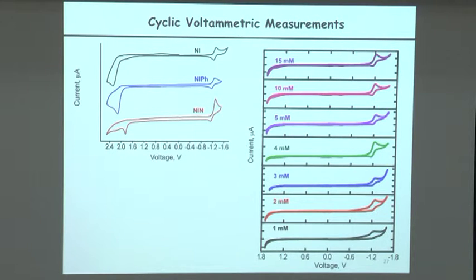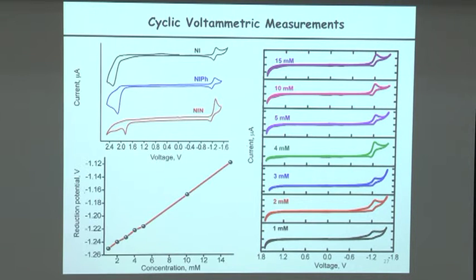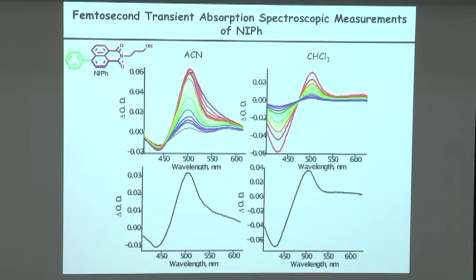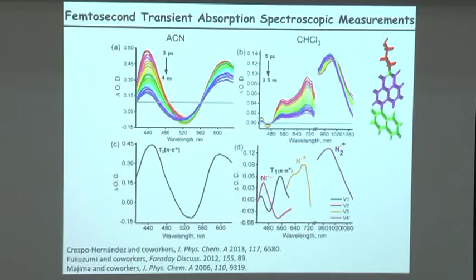It is also interesting that if you keep on increasing the concentration of the solution, you see that the redox potential gets affected, which means that this naphthalenimide chromophore gets easily reduced as you increase the concentration, which is in a way really good for the ultrafast charge separation followed by slow recombination that we are looking for. I will skip one or two slides here and show one particular slide, the structure that we have created from donor on donor, acceptor on acceptor system. This is how it looks like.